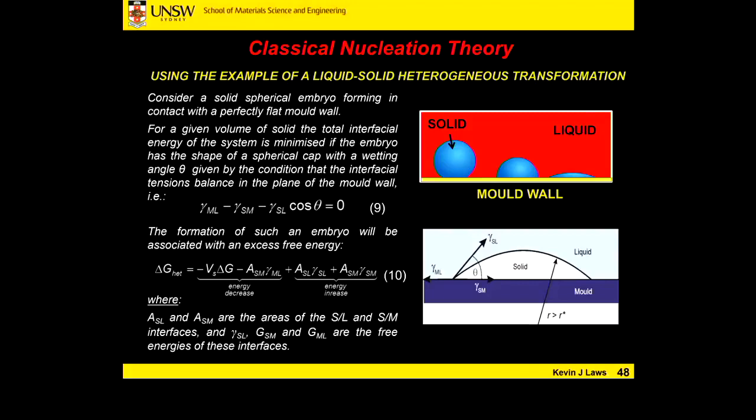Now, when we're looking at the case of a heterogeneous transformation, we're just going to look at the simple case of a mold wall in our solidification event. The case is very, very similar. We've got energy factors associated with the size of our solid particle. We've also got additional energy factors associated with interfacial energies between the liquid and the mold wall and the solid in the mold as well, which will restrict how this particle can grow.